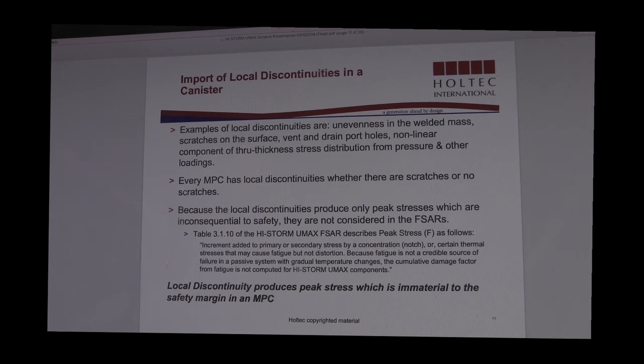And in fact, we make that conclusion in the UMAX FSAR. I pointed out Table 3.1.10. The last sentence in that paragraph I excerpted says, because fatigue is not a credible source of failure in a passive system with gradual temperature changes, the cumulative damage factor from fatigue is not computed for the UMAX components. So fatigue is a non-credible failure mechanism for the MPC canister. So fatigue is not a concern when we consider peak stresses for the canister.